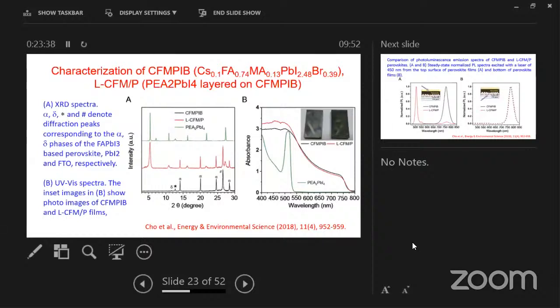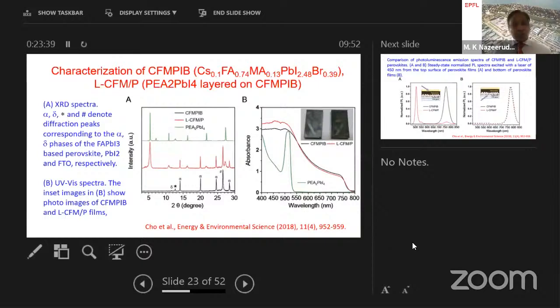Yes, we deposited a layered perovskite on the top of three-dimensional perovskite. Now you can see the characterization techniques. One, we are using XRD. Now on the right side, the B panel shows the absorption spectral properties of the two-dimensional perovskite. That's phenylethylamine lead I4. So this is the composition, and this is the absorption spectral properties.